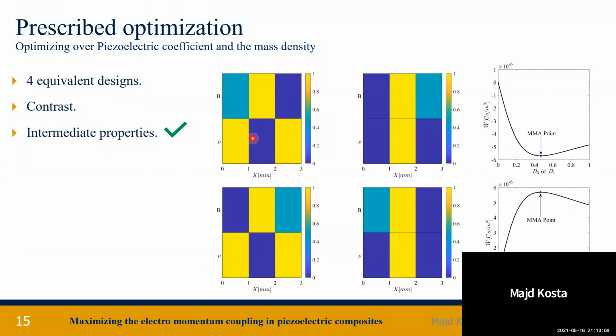And in here, we can see finally the 4 equivalent designs that have been discussed before. One can be obtained from another by flipping the value of the piezoelectric coefficient, you can see it in here, and opposing the values of the mass density. One goes to 0 and 0 goes to 1. These two steps together give us the same value of W with the same sign.